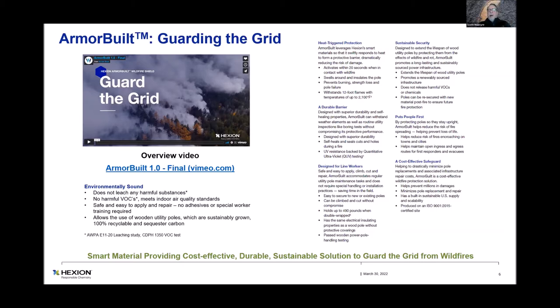This stuff is really a smart material. It activates within 20 seconds of seeing the temperature that would activate it, right around 380 F. It swells around and insulates the pole. It prevents the pole from burning. And where it says withstands 12 foot flames, that should not be in there. That should have been edited out.